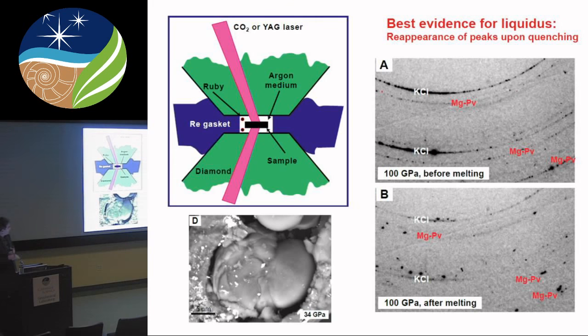And I don't show you the one in between because there's nothing on it. There's no bridgemanite. This is after melting. We see those peaks are now a couple points here and there. It's recrystallized. Here it was not molten yet. So the peaks arise from the glass crystallization, and here the peaks are from quench. And this is the shape of sample we obtain. This is a second place where we've done the melting before.